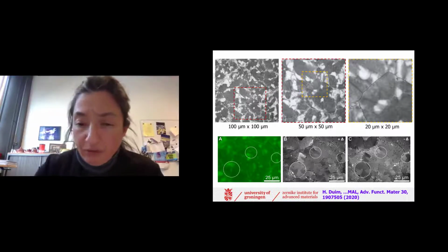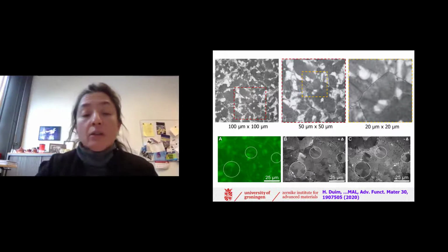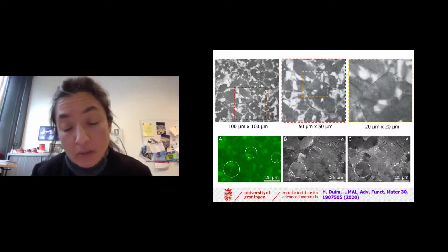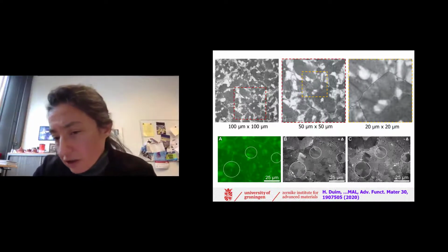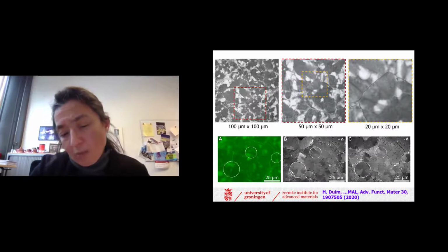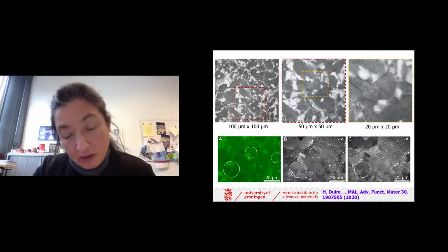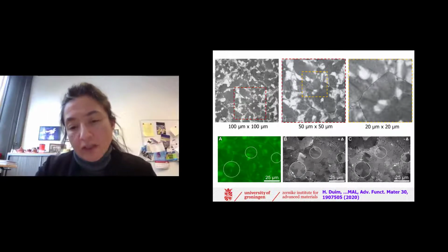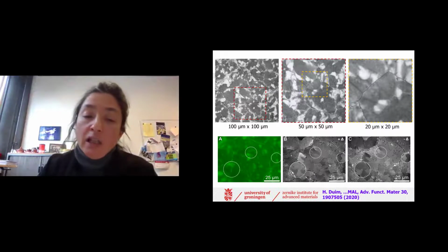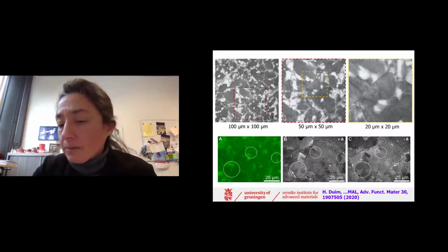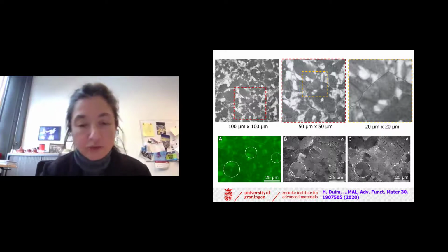Now, of course, the first thing we thought was that these inhomogeneities could be indications of crystalline orientation. So then we did some transmission microscopy with different polarization. And indeed, we saw some little variation by changing the polarizer orientation. However, it doesn't look like the bright spots correlate. Here you can see the photoluminescence in wide field and the two transmission images at different polarizer angles, done on the same spot. So actually there is not a one-to-one correlation of the bright region with, let's say, polarization difference due to crystallographic